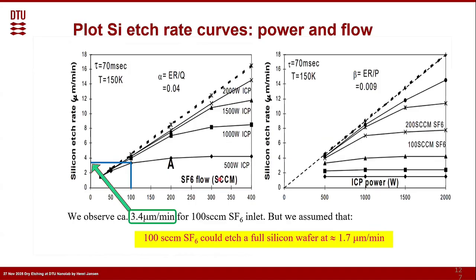And now we look again at these two curves, and look at what we see. At 100 sccm and 500 watts, we hit this point. It's in fact 3.4 micrometers per minute. But we just found theoretically that it would be 1.7 micrometers per minute. So we have double. We are etching much faster than our assumption.